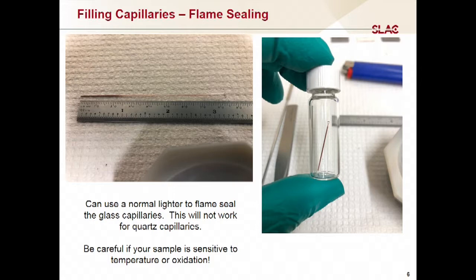And what might happen, and I've seen it happen, is if I change the phase of this little bit of powder that's on the wall, now I've kind of seeded the system with a different phase, and over time the entire thing may transform. Just because now I've introduced a different crystalline phase, I've nucleated something, that phase can grow if it's lower in energy than what I have here, and so I may have just destroyed my sample just by trying to seal the capillary. It's very difficult to sort of avoid this coating onto the wall, so this is something you want to consider before flame sealing. Having told you the issues, this is what I do 90% of the time. It's usually not really an issue, but you do want to think carefully about it and be kind of careful.